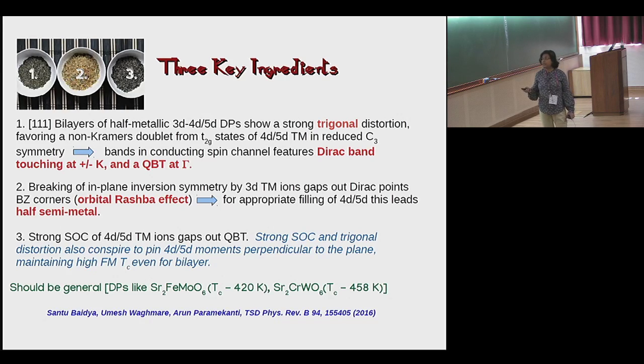It should be a general mechanism, like you can consider iron molybdenum double perovskite, chromium tungsten double perovskite. All of them, by making such a kind of bilayer, it should be possible to drive a quantum anomalous Hall state with a rather high temperature.